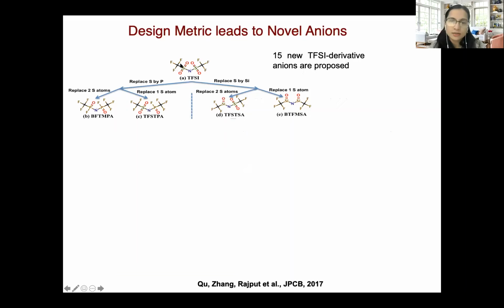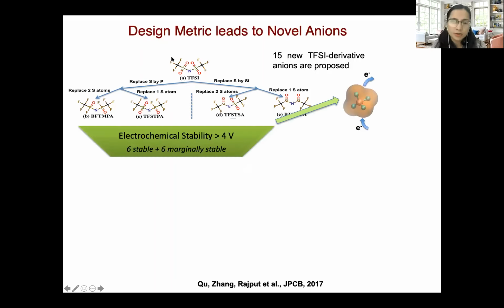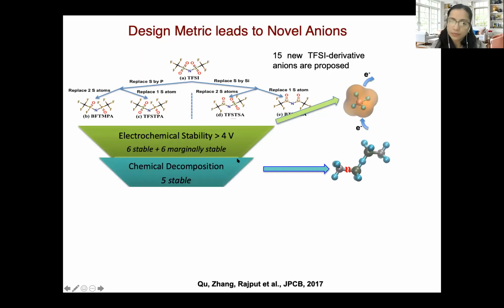So we replaced the sulfur with either phosphorus or silicon. We attached different functional groups to this molecule and derived 15 new molecules from this base anion. We then tested them for their electrochemical stability by giving an electron to the molecule and taking away an electron and ensuring that they're stable up to 4 volt. So from 15, we screened down to 6 stable molecules. We then tested them for their chemical stability, again by breaking each bond in different chemical environments and ensuring that they remain stable. So out of 6, we screened down to 5.